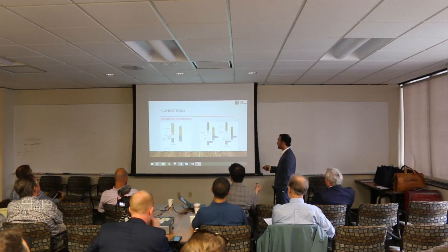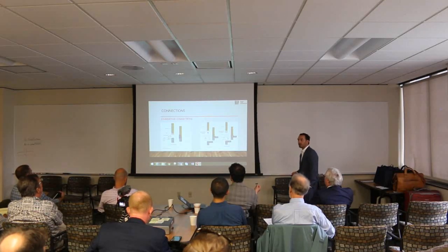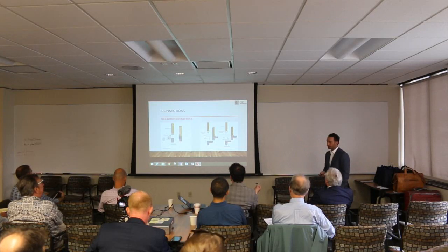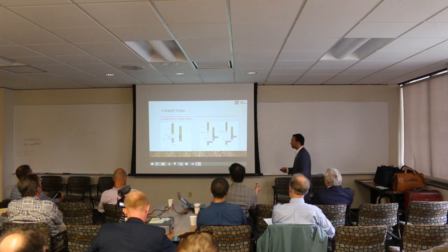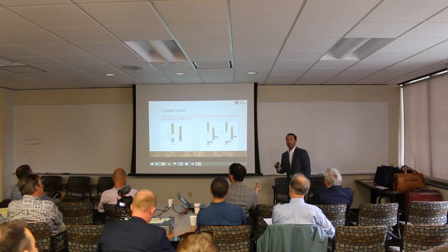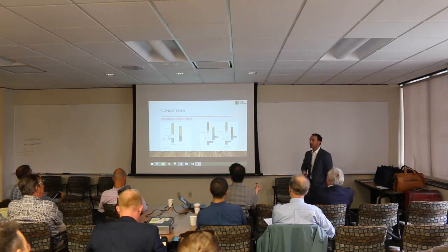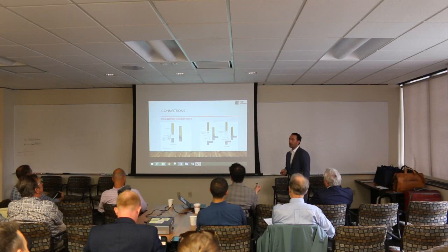Something to think about, though, is as you set this panel down, you have the interface of the moisture barrier there you need to deal with, same as any other lumber. They don't recommend that you set this right on there. You need to pay attention to that. As well as thinking through when you put a CLT panel down that's going to be cut so straight and so flat, how do you interface with a material like cast-in-place concrete that has waves and sweeps to it? It's not perfectly flat. How do you deal with that? So there's some interesting challenges there to consider when you put those together.